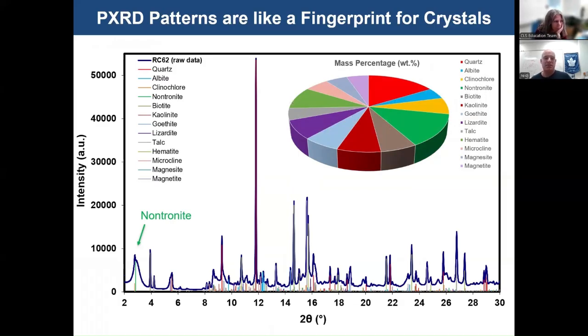In this specific sample, the largest components are the quartz, which we looked at previously, and a mineral called nontronite. The broad peak at low angle in this pattern is due to nontronite, which is a type of clay mineral with a very small crystallite size. And that's why this peak is so broad.